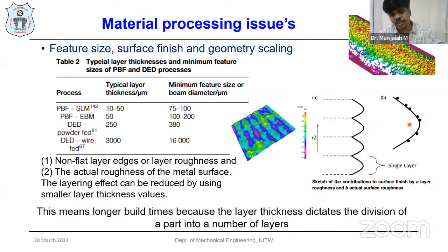Yes, the stair casing effect and this kind of defects can be minimized, but we have to reduce the layer thickness. This means the number of layers is going to increase, and it takes too much time, a longer build time, because the layer thickness will dictate the division of the entire part into a number of layers.